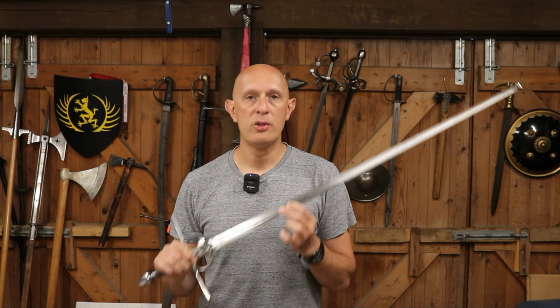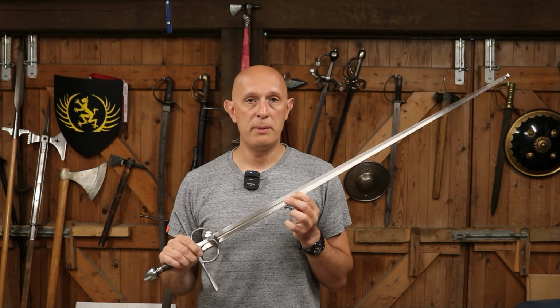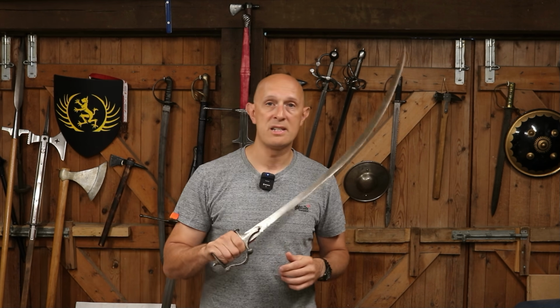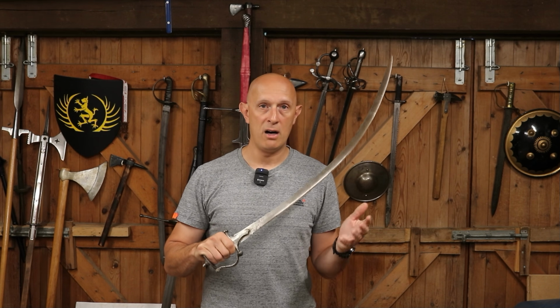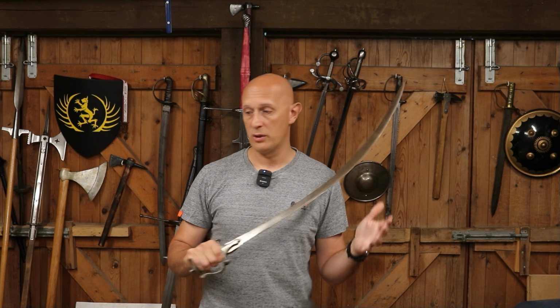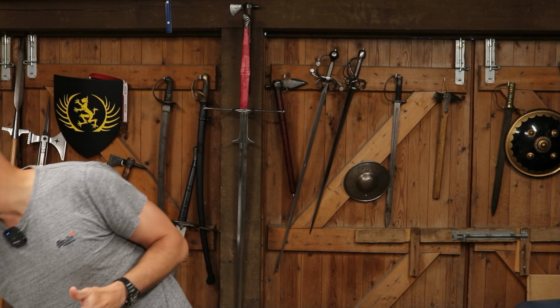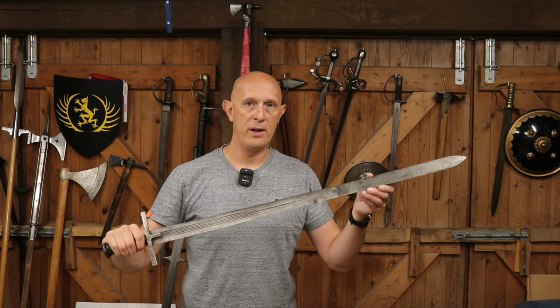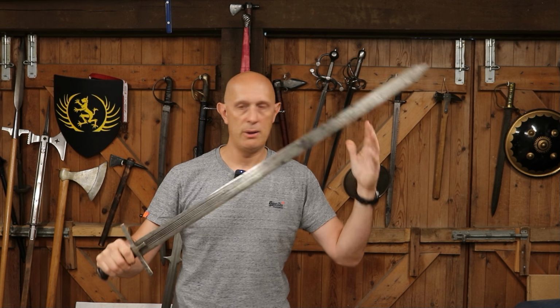However, a good medieval blade you could expect to be 40-45 Rockwell at the edge, and it is notable also that if we look at Indian swords we get a similar degree. They are usually about the same as a European sword in terms of edge hardness, and that also goes for other spring tempered African and Asian swords.